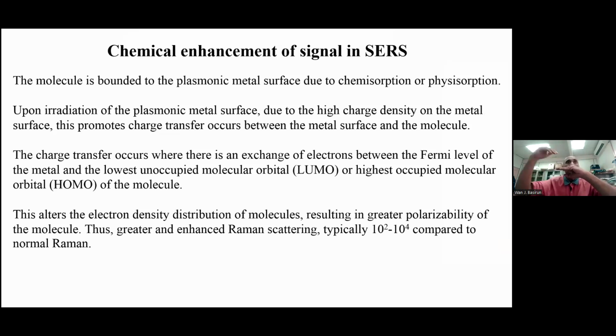So when you shine the laser onto the molecule, the electrons of the molecule become agitated, or move to the opposite side, and then you promote charge transfer from the metal to the molecule. Then you get the charge transfer effect, and this charge transfer will contribute to the chemical enhancement in SERS. So chemical enhancement is due to charge transfer from the metal surface to the molecule.